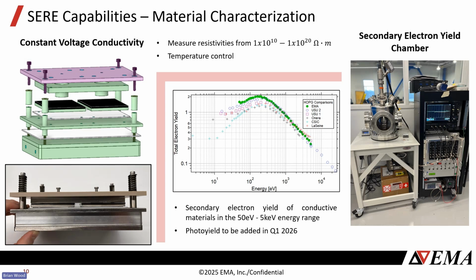This plot here is the secondary electron yield of HOPG, or highly ordered pyrolytic graphite. Our results are the green, and they agree reasonably well with some of the historical data that's out there. This is a really nice system we've got. We can have high throughput, meaning you can give us several samples and we can crank through those measurements relatively quickly. There is difficulty with trying to measure insulators in this system, so at the moment we can do conductors, but we're going to be able to do insulators in the very near future.